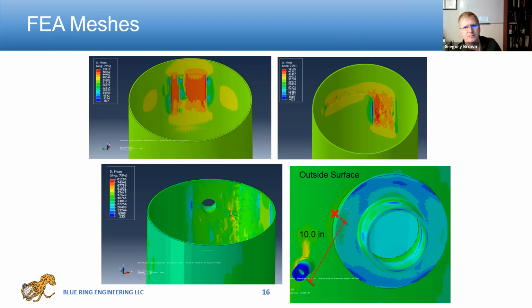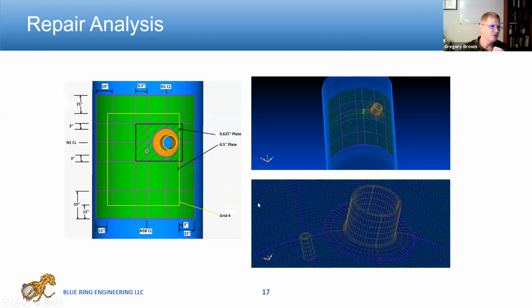To stay in operation until they could do a longer shutdown, they did an external repair where they welded patch plates on the outside of the vessel. What you can see in this picture is the diagram of the repair, where we have a 0.625 inch plate that was welded around those nozzles. It had to be done in multiple pieces so it could fit around the nozzles. The purple lines you see are the welds between plates, and then there was a fillet weld around the edge. This is not a permanent repair. This was a temporary repair until they could do a more permanent repair. How did we validate the repair?